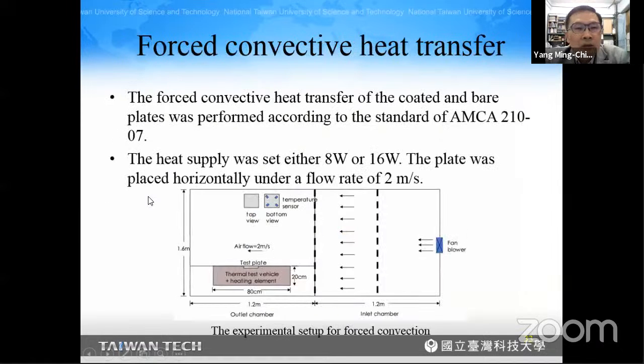Now, next is the experiment. We have two heat transfer experiments. One is a forced convective heat transfer. This experiment of coated or bare plate was performed according to the standard of AMCA 210-07. The heat supply was set to either 8 or 16 watts, and the plate was placed horizontally under a flow rate of 2 meters per second. Here we have a fan providing the air flow parallel to the surface of the test plate.